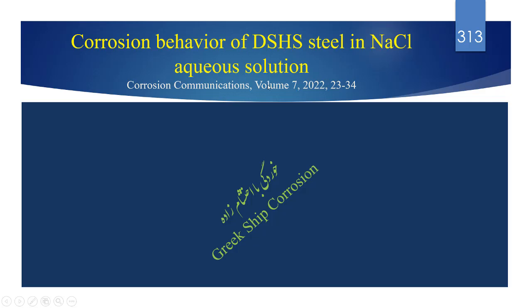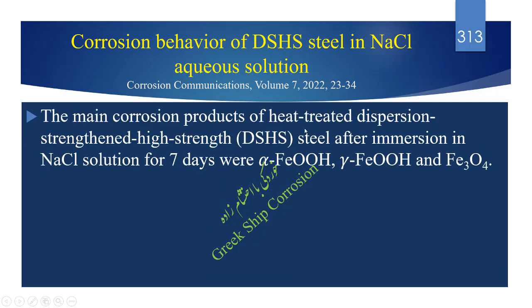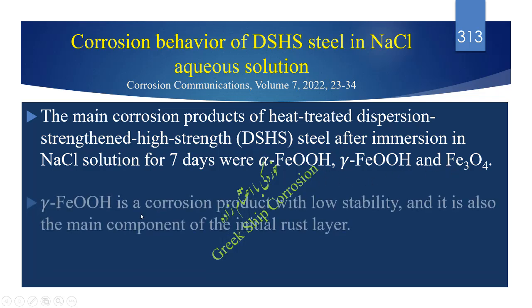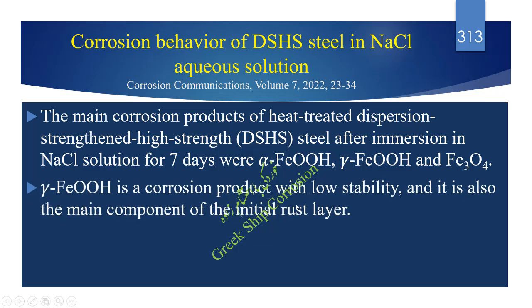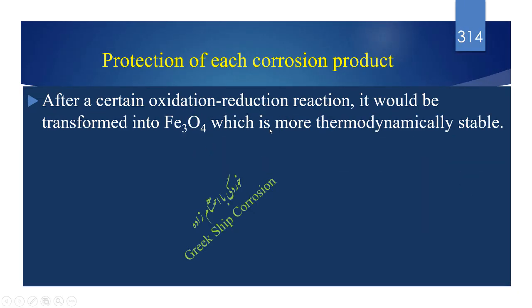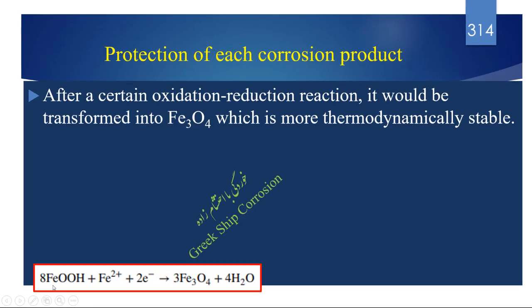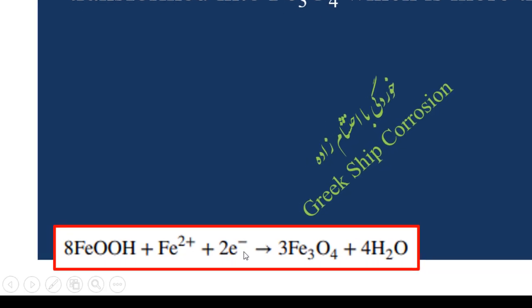Corrosion behavior of DSHS steel in sodium chloride aqueous solution. The main corrosion products of heat-treated dispersion-strengthened high-strength steel after immersion in sodium chloride solution for 7 days were alpha FeOOH, gamma FeOOH, and Fe3O4. Gamma FeOOH is a corrosion product with low stability, and it is also the main component of the initial rust layer. After a certain oxidation-reduction reaction, it would be transformed into Fe3O4, which is more thermodynamically stable. 8FeOOH + Fe2+ + 2e- yields 3Fe3O4 + 4H2O.